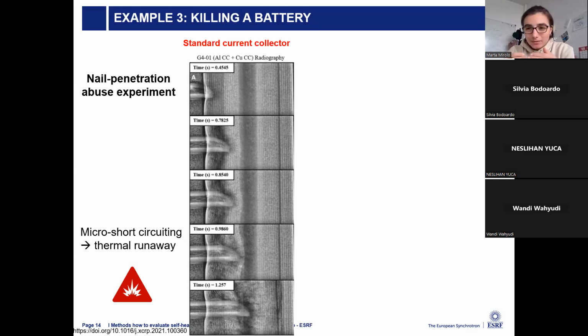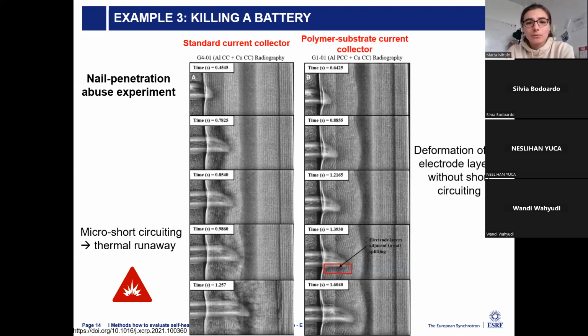So what we see is that after less than a second, when the nail is penetrating the battery, the electrodes are bending, but then due to the rigidity of the current collector, they are bouncing back. And this bouncing back leads to micro short circuiting, which leads then to the thermal runaway and to the possible explosion of the battery. However, when we look at the same battery, but with a polymer substrate current collector, the electrodes during the nail penetration are deforming, but they're not bouncing back. And this leads to the avoidance of this micro short circuiting inside the battery, and hence the avoidance of the thermal runaway, and we obtain safer batteries.